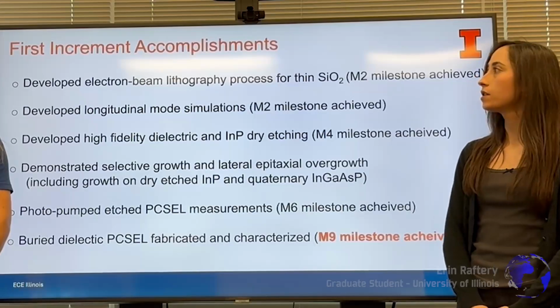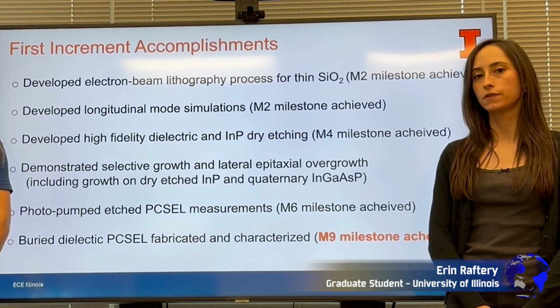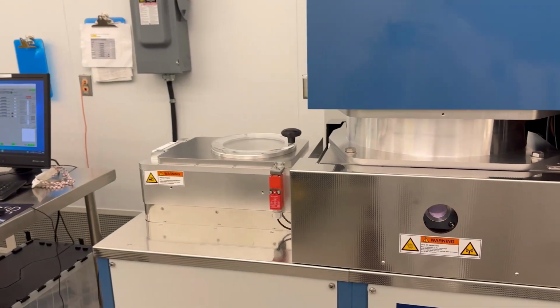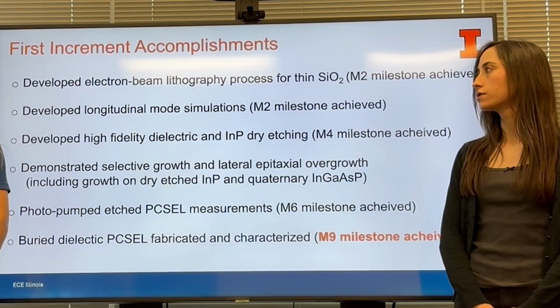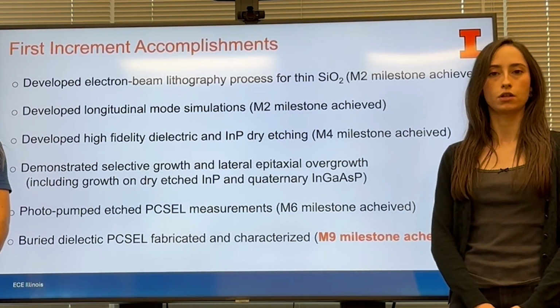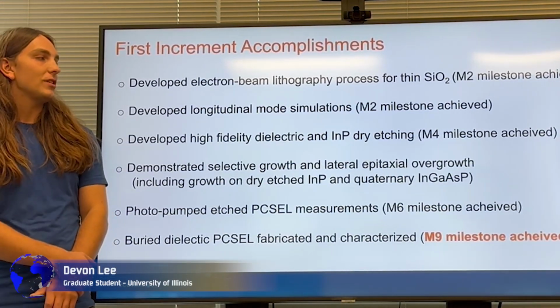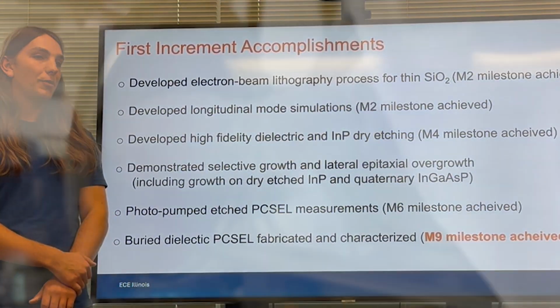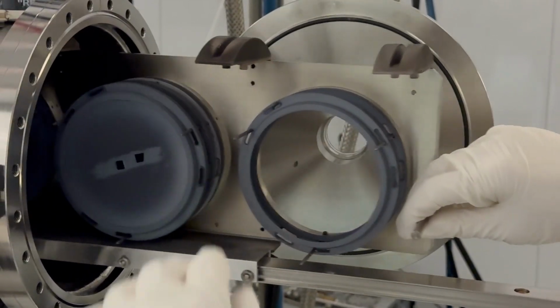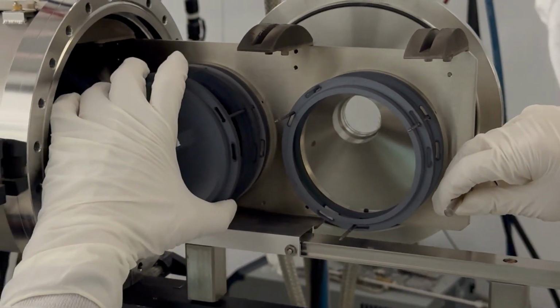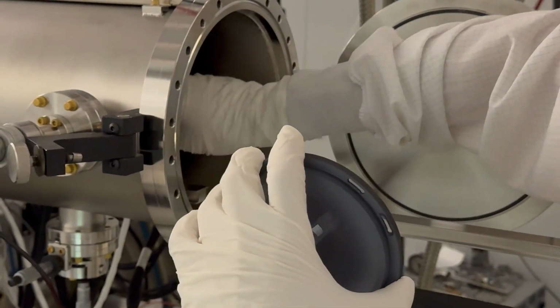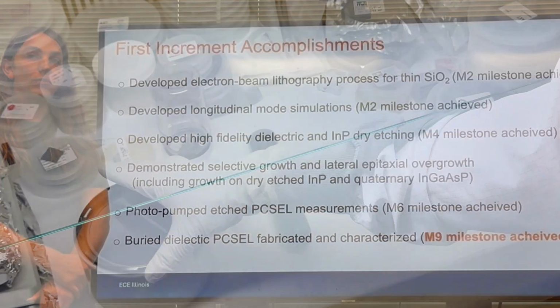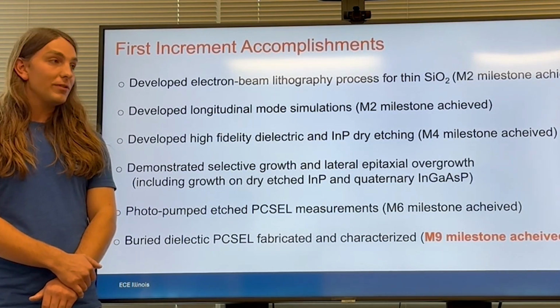So we accomplished several of our milestones in the first increment of this project. The first 2-month milestones that we achieved were the development of the electron beam lithography process for the thin SiO2, and also the development of the longitudinal mode simulations. We were also able to achieve high fidelity dry etching of both indium phosphide and dielectric, as well as achieving selective overgrowth and lateral epitaxial overgrowth, both from indium phosphide and from a quaternary indium gallium arsenide phosphide, which to our knowledge is the first that's been achieved.